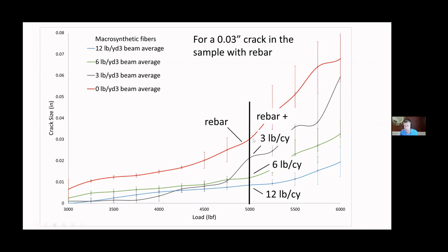Then we can see this is where our rebar is, and here's where our 3 pounds of fibers, that's about a 30% decrease in the crack size. Here is 6 pounds, that's about a 60% decrease in crack size. And here is 12 pounds, that's about an 80% decrease in crack size.